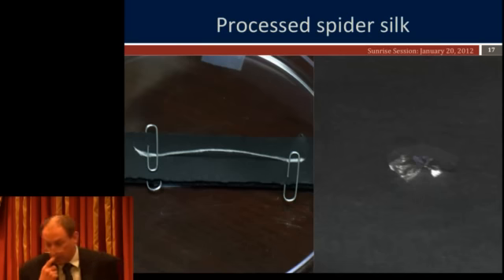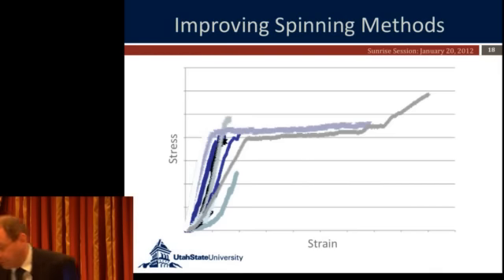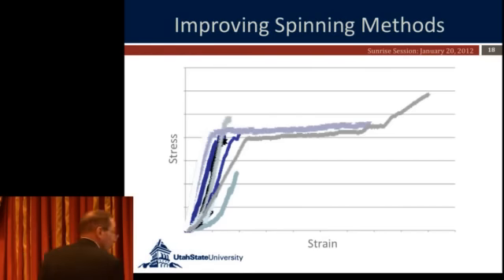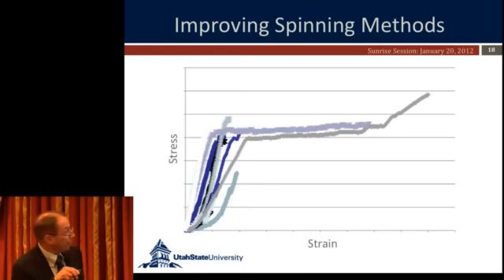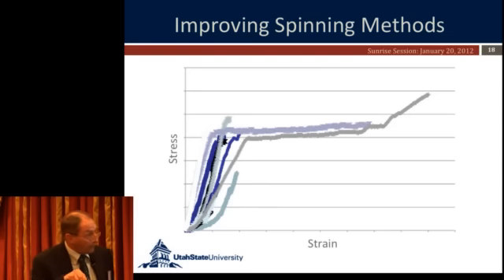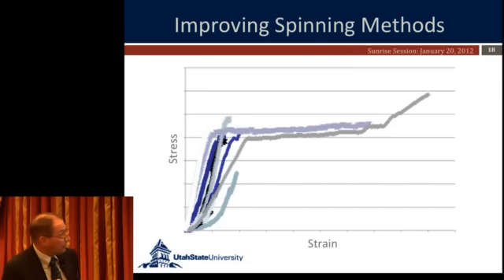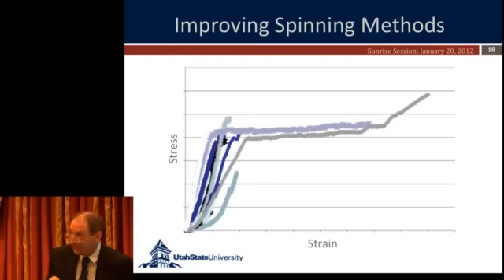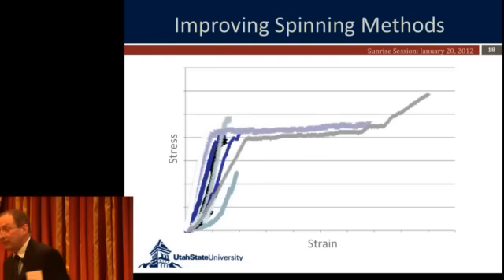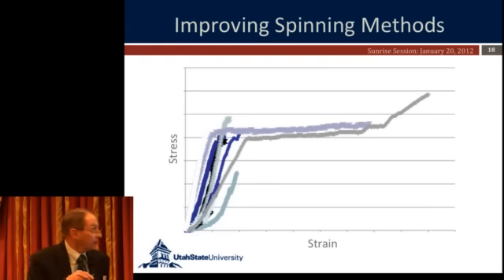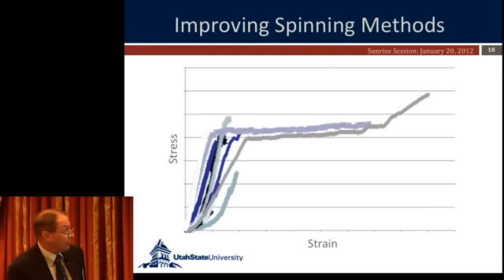Now, one of the problems that we encountered in trying to spin the fibers was that we had very poor consistency. So here is force, that's how much force it takes to stretch it. This is how far it stretches. And you can see that you have some that are really lousy, you have some that are not too bad, and you have some that are really, really good. Now, if you're trying to make materials out of it, that's not a very good situation because you have a twofold difference in how much strength it has. You can see we've got a 10, 15-fold difference in how far it stretches.